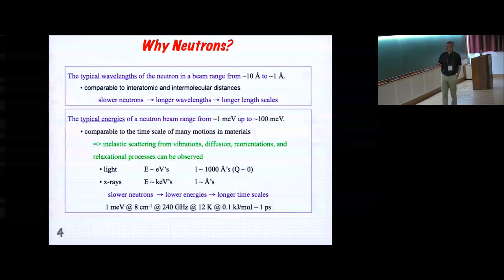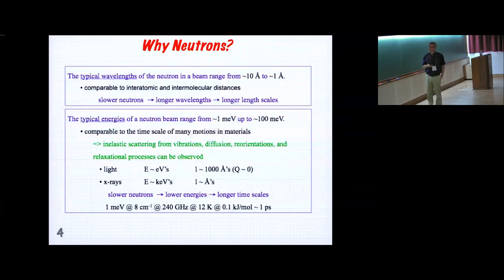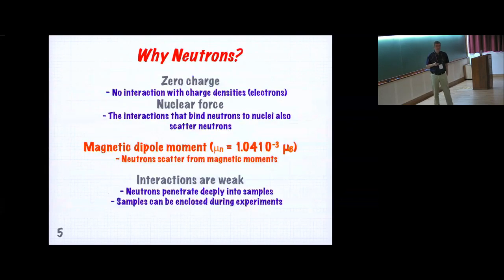With the neutrons, depending on what tools you use at home or what you read, 1 meV has about 8 wave numbers for those in light scattering, or a quarter of a terahertz, or close to 12 Kelvin. So these are the kind of energies that we know are appropriate for thermal excitations and spin waves and so on. For us, in this magnetism meeting, another important thing is that the neutron has a dipole moment, and so we can probe the spins in our system directly. So that's our biggest strength.